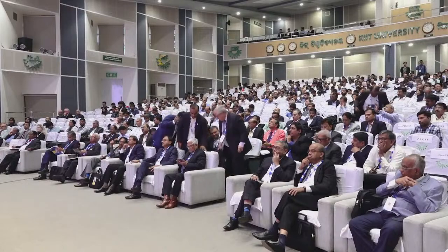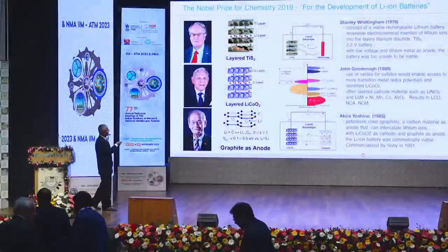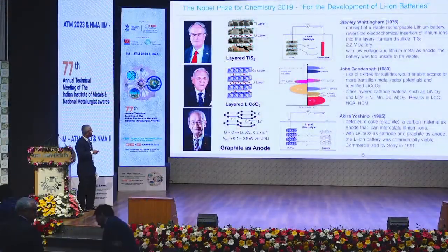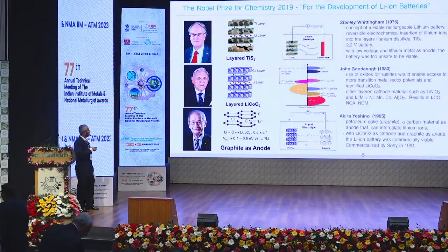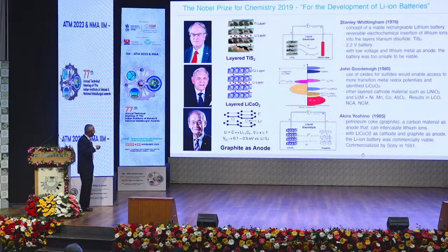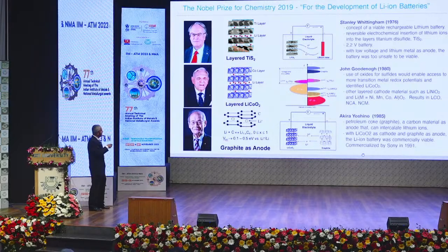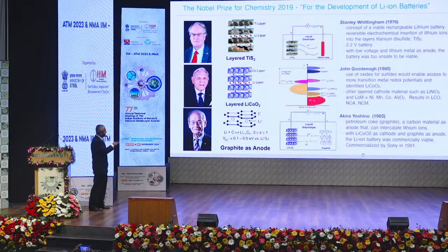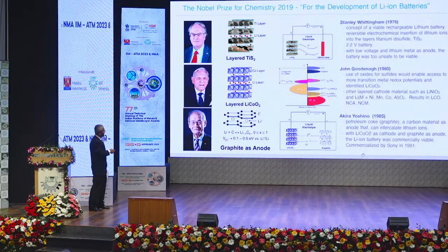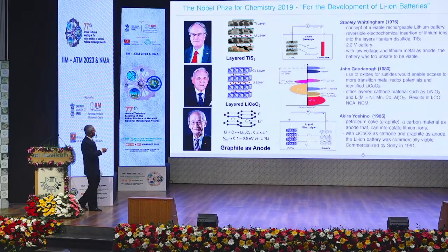So to summarize, this is the Nobel Prize work. Stanley Whittingham demonstrated the concept of a viable rechargeable lithium battery, with reversible electrochemical insertion of lithium ions into the layers of TiS2 at 2.2 volts. With low voltage and lithium metal as anode, the battery was not safe enough to be viable. John Goodenough's group found that using oxide for sulfide would enable access to more transition metal redox potentials, and identified LiCoO2.